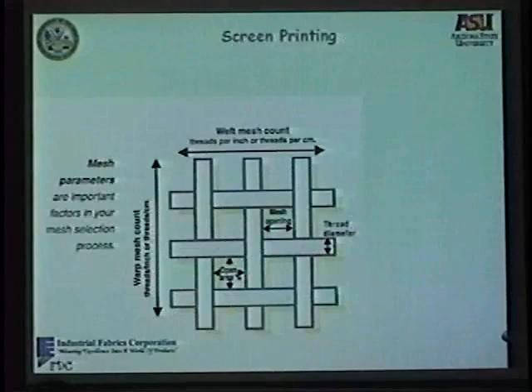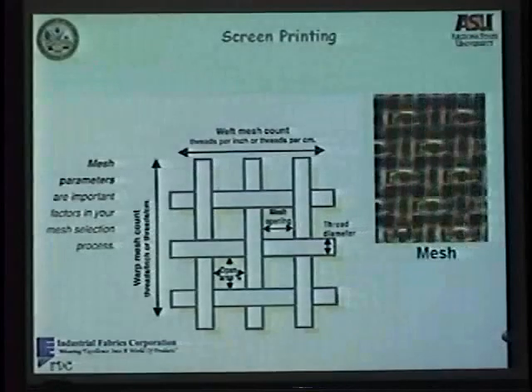We were also the first group in the world that used screen printing to print OLEDs. And the first time we sent this back in 1999 to be reviewed, the referee thought we were crazy because they couldn't believe we can print 90 nanometer thick layers. Later on we were able to print 10 nanometer thick layers with uniformity better than spin coating. So here, screen printing is very easy. It's like a mosquito mesh, and these are the openings. You force the ink through here.